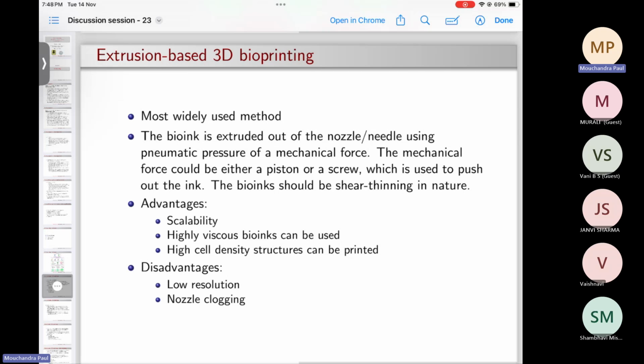And the space between the two filaments you won't be able to see, they will most likely merge, if you're using a pattern where the space is less, and you won't be able to differentiate between the two filaments that well. That is why I'm saying that it gives low resolution 3D structures. And also, since this technique requires the use of highly viscous bioinks, if your parameters are not optimized, most likely during your initial trials you will see nozzle clogging happening. If your nozzle clogs, then your robotic arm will just move without dispensing anything onto the bottom, because that means your nozzle is clogged.